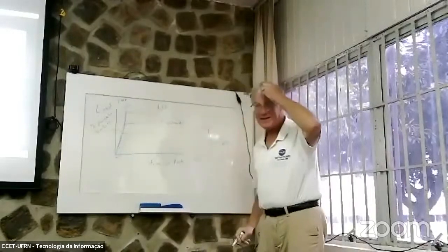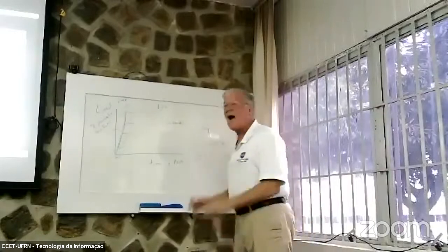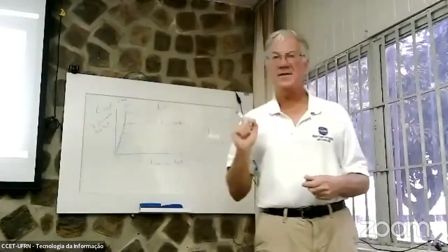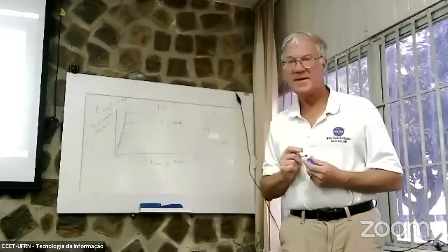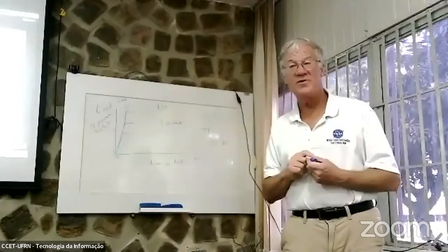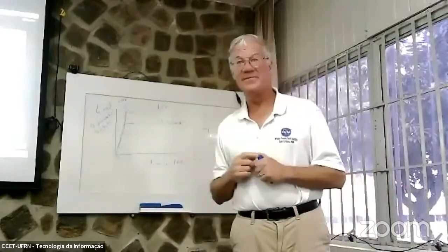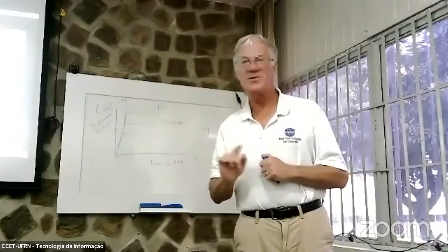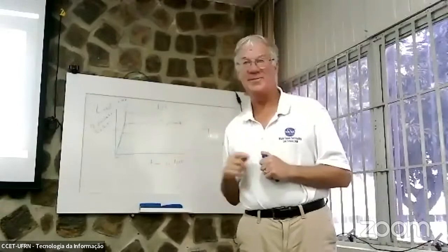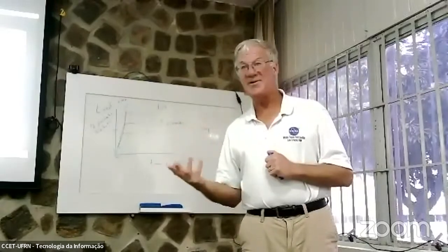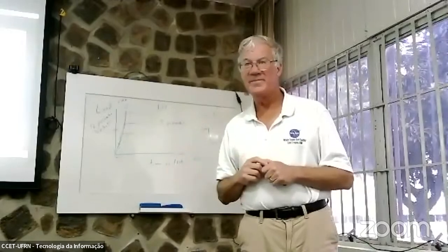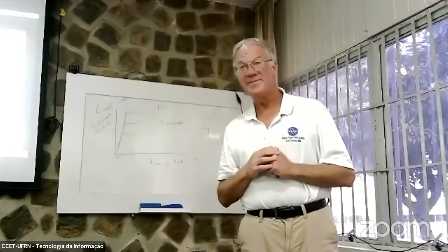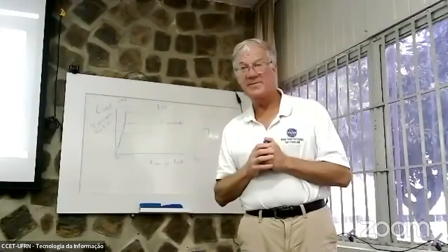This is proof. So a question is, one of the theories in this community is that by proofing it, you are creating damage that sooner or later you will see. Versus the possibility of you've eliminated all the weak and it'll last forever. The theoreticians who have never conducted a single experiment were assuming that it's going to hurt. The people who have real practical experience said, oh, it'll last forever. Guess what our experiment showed? It lasts forever.